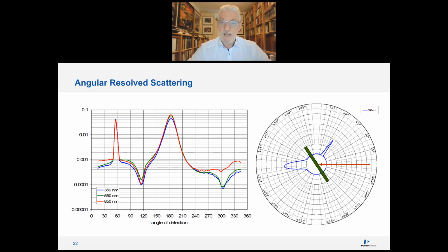The angle of incidence was constant, I think it's 45 degrees or a little bit less, and the detector was moving around the sample just to record the intensity for different angles, different directions. So that's one of the results you see here.